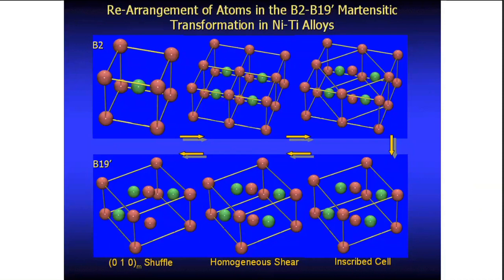That's dilatation. And shear would be that you're having a pure shear where one face is shearing in relation to another. And if you have shuffle, it would mean a plane of atoms are shuffling like cards. Like if it's for this case, it would be this plane shuffling with respect to each other, where the center of gravity has not changed, and the purpose of this would be slightly moving this atom to another location of choice. Now, it so happens in the general case, all the three are required to move the atom to the final position in any phase transformation, which is diffusionless.